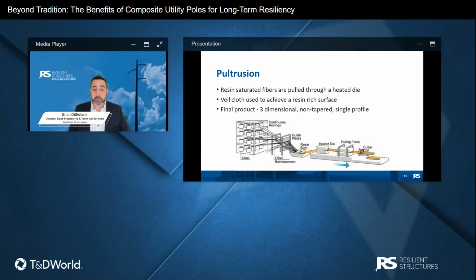One advantage of this particular method, though, is its continuous operation. Parts can be manufactured indefinitely and then cut to the desired length, all without interrupting any production. Pultrusion also produces a uniform, non-tapered profile. However, the height of the pole made through this process is limited by its base diameter. So larger dies would be needed for wider bases, which could require having to change out equipment, causing production downtime. Also, using polyurethane resin in this manufacturing process presents many challenges and is quite difficult.